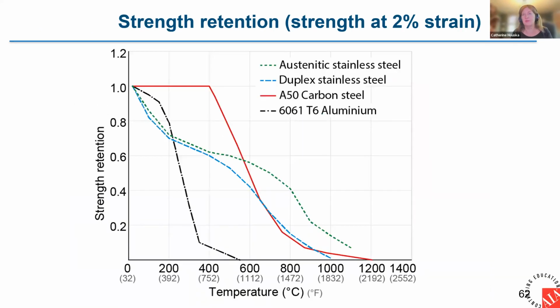That was a tunnel fire, which is a bit different. But there is a lot of data out there in applications where the fire temperature is lower. Typically not an industrial building, but it could be a building for other purposes. You can see that the austenitic stainless steels retain their strength as you get to higher temperatures better than carbon steel, much less aluminum, which doesn't retain its strength at all.